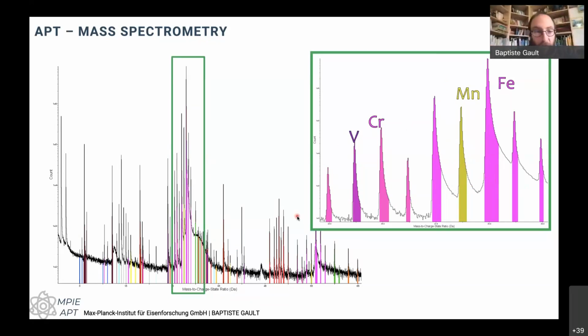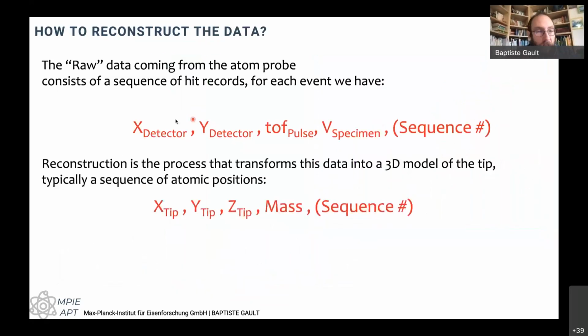That depends on the elements and the strength of the field. But that's the first information we get, is the piece of material that I've basically broken down atom by atom. I can tell you what it contained initially. And then, as I said, we have these detector coordinates and the time of flight. And then we sort of assume that the atoms, the sequence in which we detect them, must reflect the depth at which the atoms were initially, right? Because if you have an atom on top of another one, this one must come off first before the second one can come off.